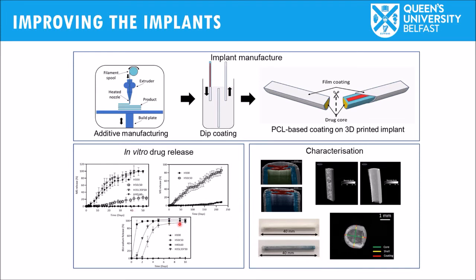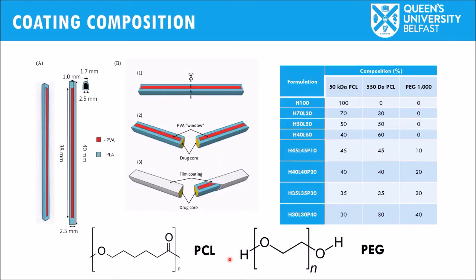So she did formulation work to prepare different types of membranes that are going to sustain the delivery of hydrophilic compounds from this type of implant. For this purpose, as I mentioned, the implants used were the ones with a large soluble window, and they were filled with the same model compounds that I described in the first example, and they were coated with a formulation based on polycaprolactone.